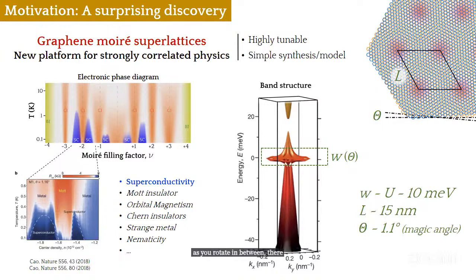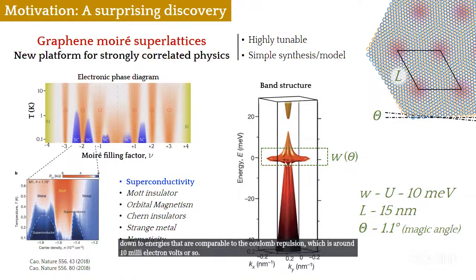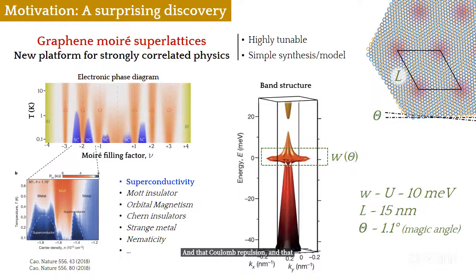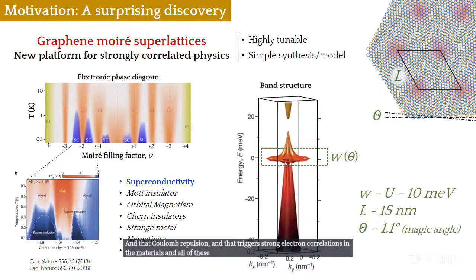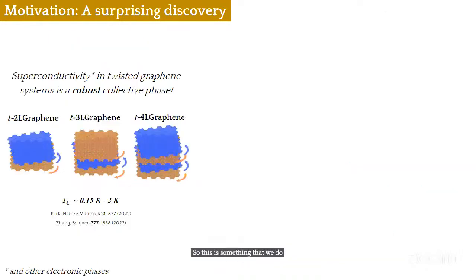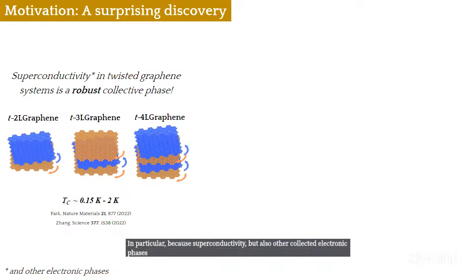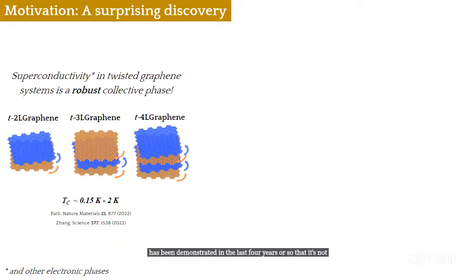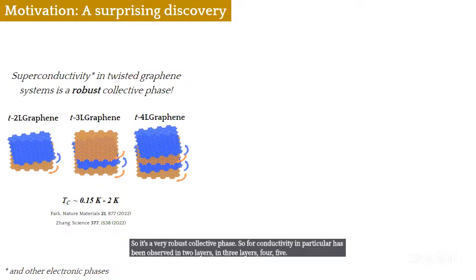There is some superpotential that the electrons feel, and the effect on the band structure is the flattening of the bands down to energies that are comparable to the Coulomb repulsion, which is around 10 milli-electron volts or so. That triggers strong electron correlations in the materials. This is something that we wanted to study, in particular because superconductivity, but also other correlated electronic phases, has been demonstrated in the last 4 years or so not to be something that arises by chance, so it's a very robust collective phase. Superconductivity in particular has been observed in 2 layers, in 3 layers, 4, 5, other stackings as well. So it's there.